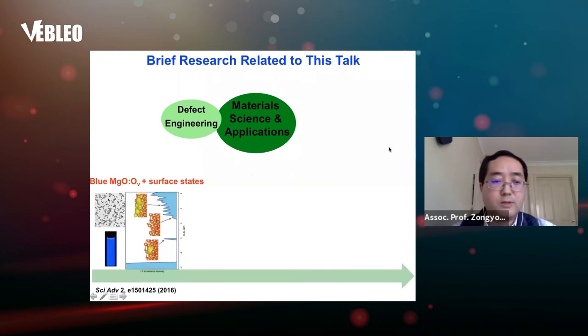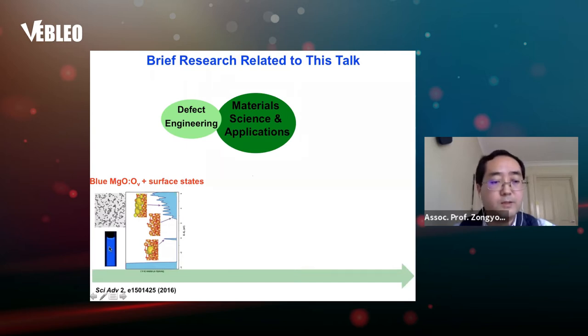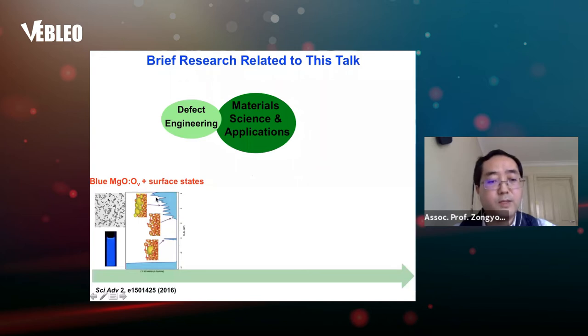The first work, published a few years ago, is about magnesium oxide (MgO). We tried to introduce oxygen vacancies and generate some surface states. We found that the surface states act as electron transport layers — electrons transfer through different states and accumulate at the bottom, then emit blue light. We call this 'blue MgO.' The electron only stays at the bottom of these states and will not go to the conduction band of MgO, so MgO will not be reduced.